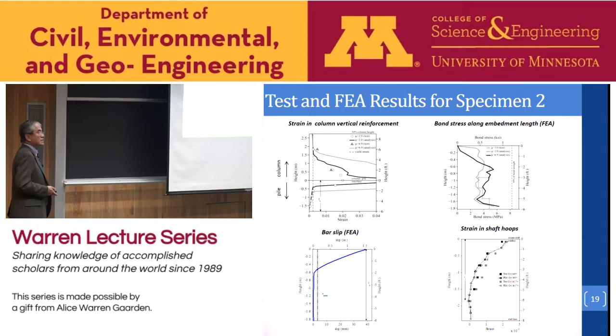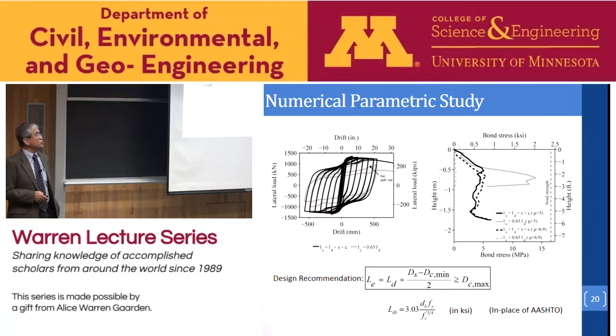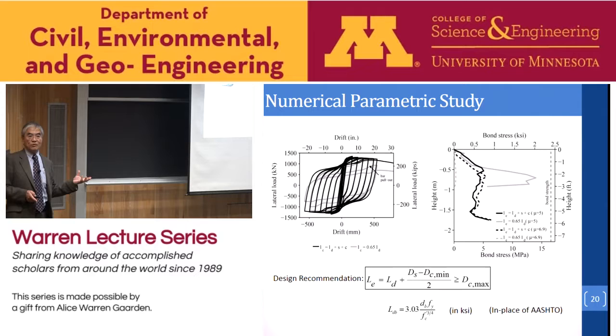This shows the slip of the bar inside the shaft, and this shows the comparison of the measured stress in the confining hoops as compared to what is predicted with the numerical model, which seems to be pretty good. After that, we used the model to do a number of parametric simulation studies. We want to know what is the minimum required, whether what we used in the test is indeed the minimum, or whether we can further reduce that.